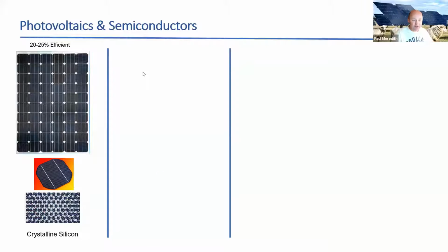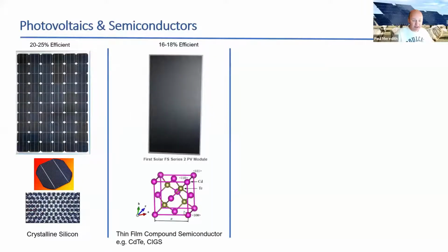There are other types of semiconductor-based photovoltaics. This one is a so-called thin film semiconductor panel. This silicon panel, for example, the silicon solar cells are about 500 microns thick. That's about 0.5 millimeter. Each of these individual cells is about 0.5 millimeter thick. Whereas this particular thin film solar panel, made from a material called cadmium telluride, is only about 50 microns thick. So maybe 10 times thinner than the silicon panel. It uses less semiconductor, therefore, but it's not quite as efficient. It's about 16 to 18% efficient, I think, is the world record at the moment.